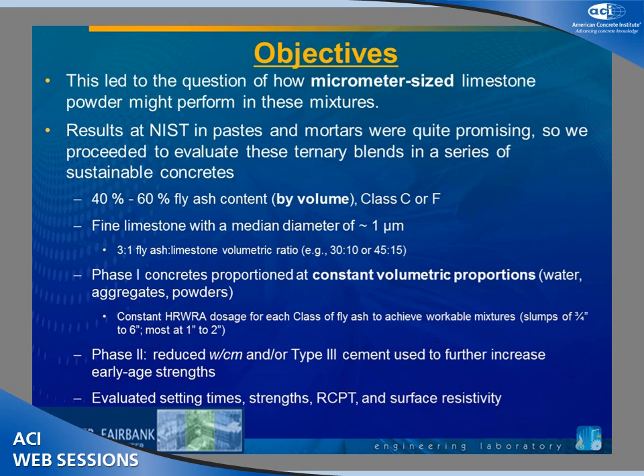So we did this in 2 phases. In phase 1, we made concretes where we maintained constant volumetric proportions. We didn't want to do this at a constant water to cement ratio by mass because of the significant differences in specific gravity between the fly ashes, the limestone, and the cement. So we did everything on a volumetric basis, so all our mixes have the same volumetric water content. So if we see strength effects, if we see durability effects, we know it's not due to the fact that the mixtures have different amounts of porosity because they had different water contents.